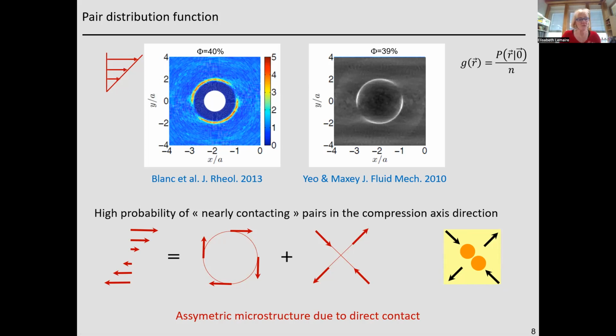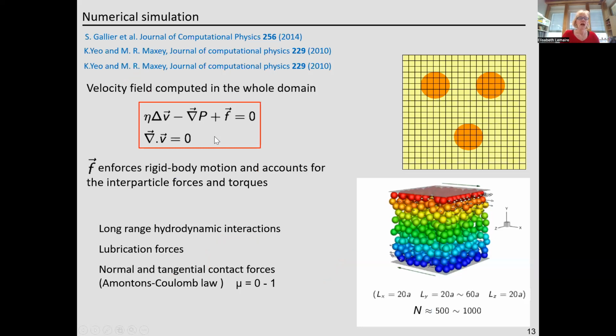It has been shown that this asymmetry of the microstructure is a direct signature of direct contact forces between particles. So the asymmetry of the microstructure just means that direct contact between particles exists in non-Brownian suspensions. And the effect of this contact on the rheology of suspensions is really, really huge.